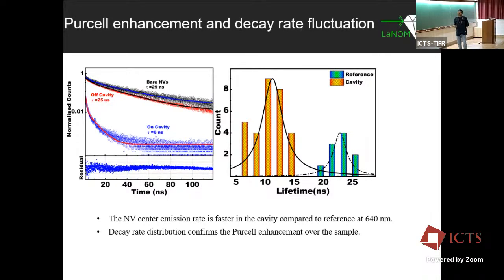Answer is no. Okay, so we did a lot of measurements and we picked up many NV centers. Some may be very well coupled with the cavity, some may not be that much. So it can also happen, even though your samples are very nice, even the PL spectra also show it, that all your NVs may not couple with the cavity. So it is a more stressful experiment, and the sample growth is the main key factor here. If you have nice sample growth techniques, controlling these emission parameters is very interesting. And you can see that at any rate, the sample shows a better decay rate compared to the reference sample. And this is at 640 nanometer. We did it for 660, 700, and 600 nanometer.